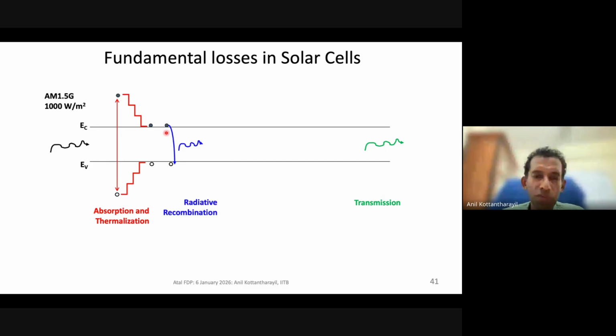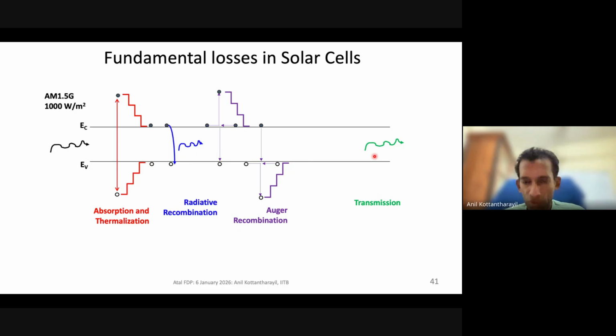And then out of this generation, we have seen some losses due to radiative recombination. So there's some thermalization loss, but even the remaining energy is not completely preserved. A part of that is lost due to radiative recombination. This light is escaping the semiconductor, and there are some solar cells where people try to reuse it. It's called photon recycling. We will not go into the details here. That's important for solar cells made of perovskite, gallium arsenide, and things like this. And then you have Auger recombination, so there can be losses, and these are fundamental losses. You can't do much about them. Of course, SRH recombination is another recombination process, but it's not fundamental. Theoretically, you can reduce the defect density to 0, and you will not have any SRH recombination losses.